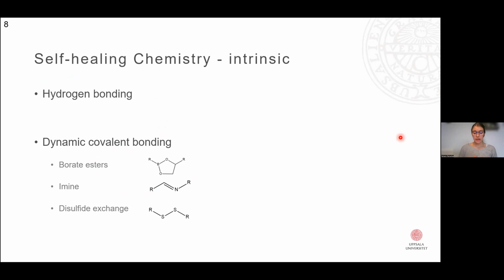So these intrinsic self-healing chemistries can be very efficient to inhibit the volume changes during cycling, and also hold the active material together. So we improve both the mechanical and the electrical robustness of the electrodes. Hydrogen bonding, I would say, is the most preferred strategy so far for binders. But dynamic covalent bonds present more mechanical stability. So they're also a good option to use in these self-healing binder systems.